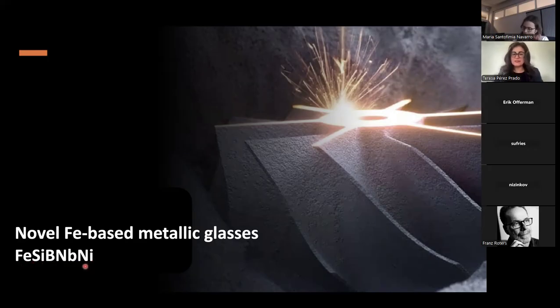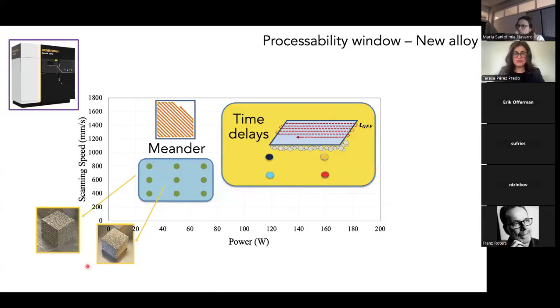As you can see, this alloy doesn't contain any of the unwanted elements that we didn't want from the beginning in this project. And they managed to increase the glass formability from about 100 to 150 microns, which is that of the commercial alloys, to 1 millimeter. So this was a very big improvement. And what we did next in this last part of the project was to see whether what we had learned regarding process optimization could be applied to these alloys to finally make fully amorphous components. And this is what I'll show you in this last part of my talk.